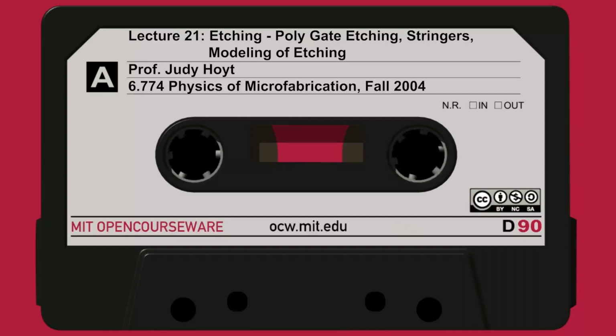So here at 10 millitorr, you get a fairly isotropic etch. It's not totally isotropic, but you notice it's etching sideways as well as vertically. And how can I tell? Because this is my photoresist, and it's undercut on the left and right side. So the line is a lot narrower than what had been designed. There's a little bit better anisotropy at a lower pressure at 1 millitorr, but now we've developed a little notch at the bottom, which, again, is not considered to be good.